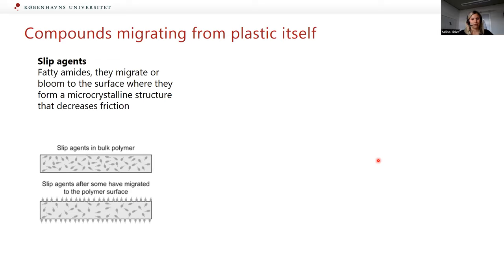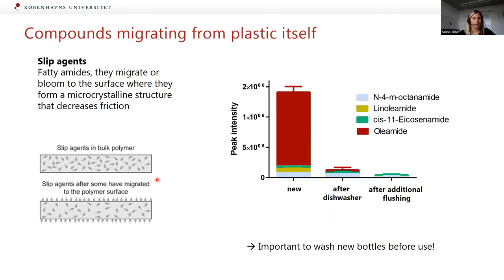Another compound group we detected were slip agents, which are fatty amides, which migrate or bloom to the surface during the production. So they are in the material, and then during the production process, they bloom to the surface. And by that, the bottle is just easier to get out of the machine. Like when you're baking and you want your cake to come out of the form, then you use butter. That's the same here for these slip agents. We detected them in the new bottles in high peak intensities. And the good thing here is that it seems that they are a lot more removed after the washing process. It's also what the producers recommend, of course, that you wash your bottle before use, and that helps for the slip agents.